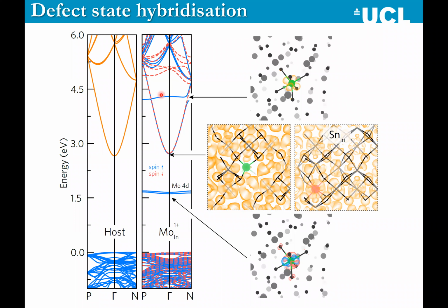And here the unoccupied state, again, is centered solely on molybdenum and is an unoccupied D state. Whereas if we compare this non-interacting molybdenum state at the bottom of the conduction band with the tin dopant in the indium site, you can see that there's a lot of charge density around the tin, meaning that the tin and the indium are actually mixing and having a chemical interaction, which is what we believe is causing the issues with the effective mass of the ITO conduction band.